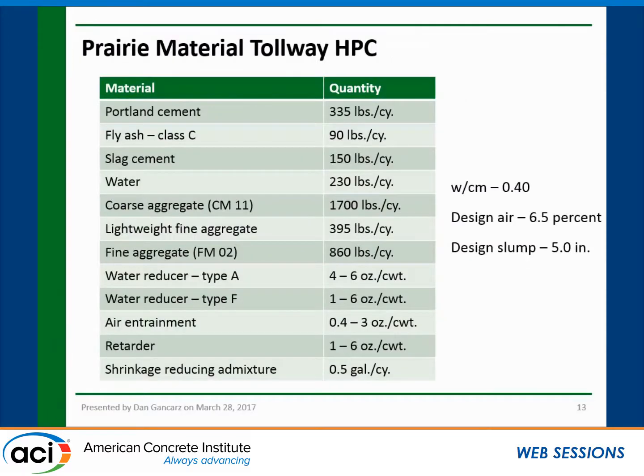penetrability. So here's a mix design that was used on 22 bridge decks over the past 4 years on the Illinois Tollway. Now it's not required to be ternary, but the producer decided to take that approach. So we have 575 pounds total cementitious, water cement ratio of 0.4, which is not like a lot of HPC mix designs you may see. It's got a lower total cementitious, a higher water cement ratio. You don't see silica fume being used, but this mix meets the performance requirements that we're looking for as far as chloride penetration, shrinkage, and then strength.